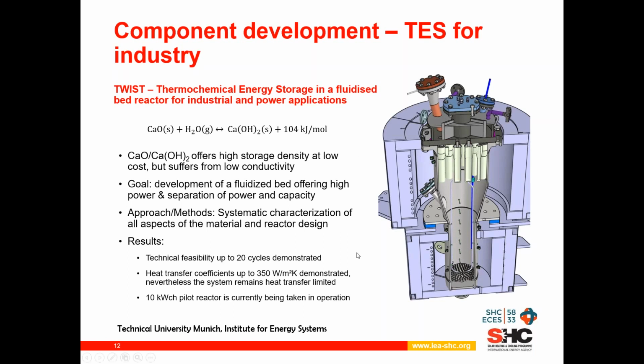This device is constructed as a cyclone reactor in which calcium oxide is being mixed with water vapor and then forms calcium hydroxide plus heat in the form of 104 kilojoules per mole. And the challenge with this reaction is to get the heat out at the proper temperatures and get the heat out in an effective way, in such a way that all the particles containing this heat are being brought into good contact with the walls of the reactor. And then this reactor is being used to have cycling, and up until now the technical feasibility was demonstrated up to 20 cycles.